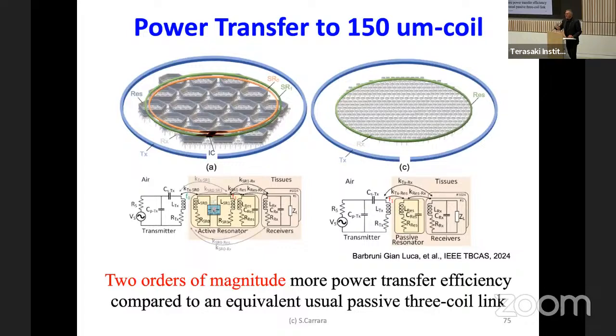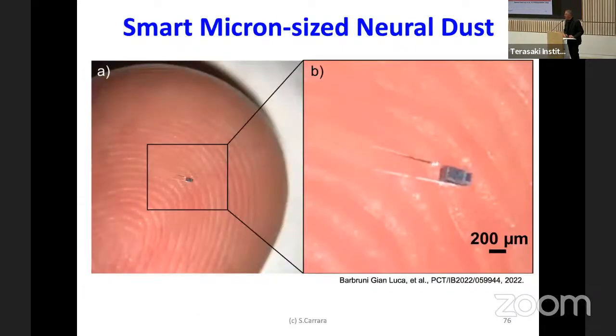We have also developed a smarter idea to receive more power by moving from a passive resonant coil to one in between the transmitting and the receiving. And you see here an electronic IC that shifts the frequency in order to be more reliable, with more power received in the first layer when we pass through the skull, and then goes high with the frequency in order to reach the different implant. And here is the implant we have realized at EPFL. You see the scale is,